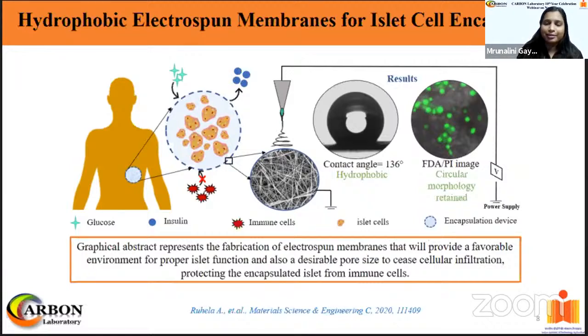Here, we demonstrate a fabrication of a polymer membrane that has pore size 0.3 to 0.6 micrometer, vital for an active exchange of essential nutrients such as insulin and glucose while ceasing the infiltration of the body's immune cells.